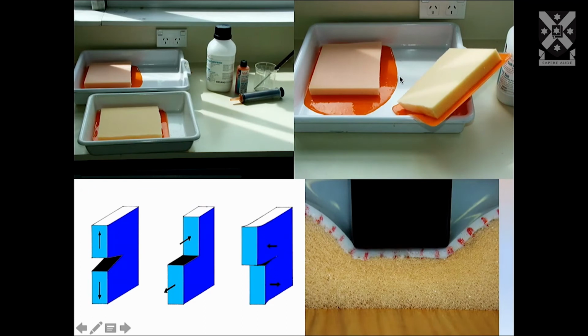So using silicone as a skin and a sponge, we were then able to impact this. And while it is dry, there's no fluid in the sponge. You can impact it as many times as you want. Nothing changes. It elastically recovers fully.